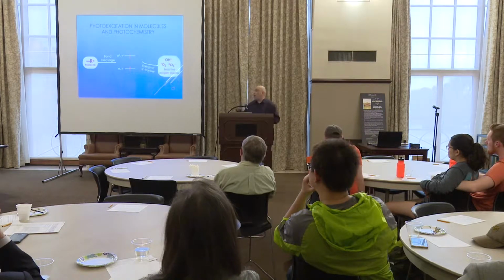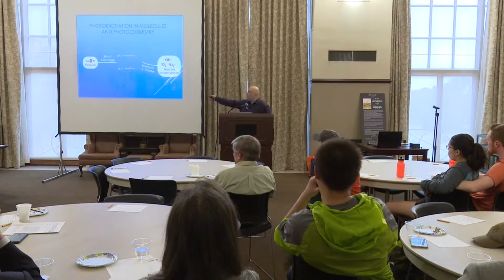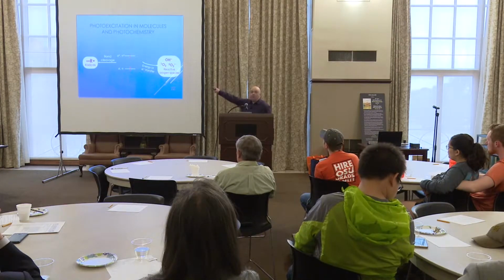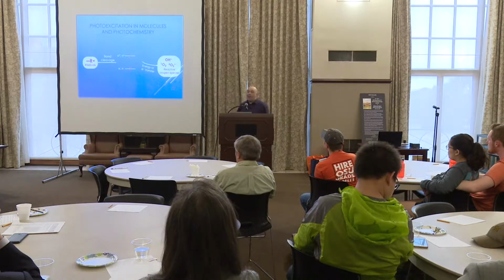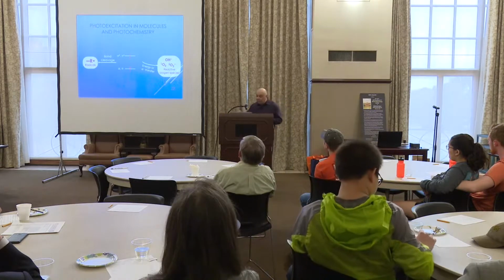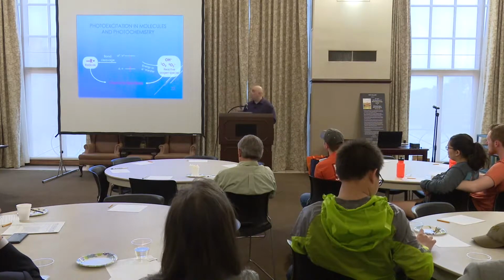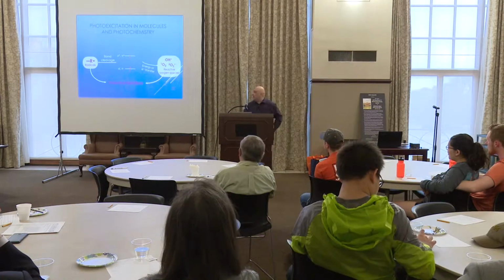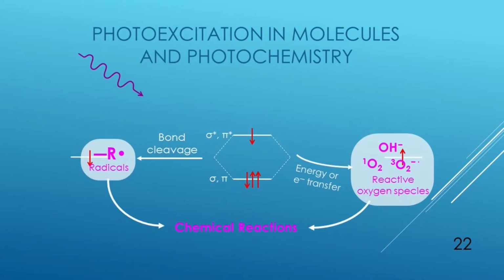So a second type of reaction can happen, where the energy of the excited molecule can be transferred to water or oxygen in the environment, and it will create reactive oxygen species. Now, in photochemistry, both of these reactive species can do things. They result in chemical reactions. So this is photochemistry. Now, for about 70 years, people have believed polymers degrade with this mechanism here by radical formation. But in our group, what we found was an alternative and more likely way polymers are actually photodegrading, which is by this pathway here. Okay, and that's what our research was about.